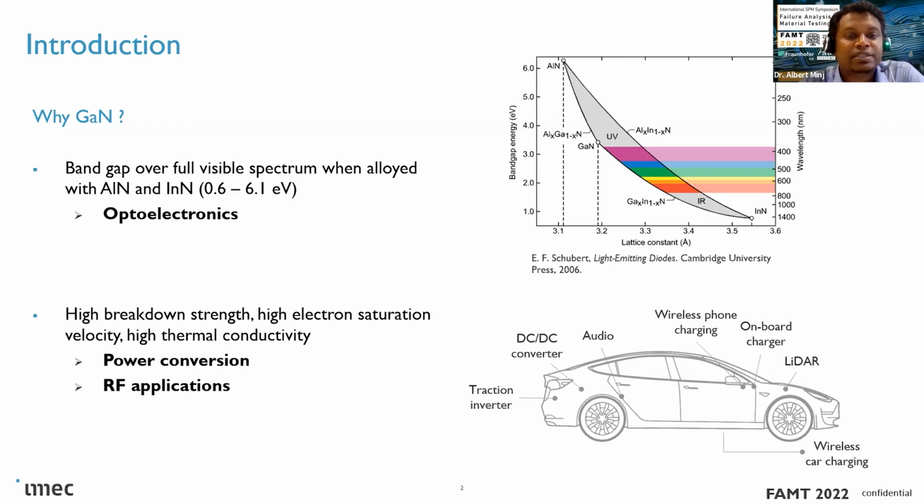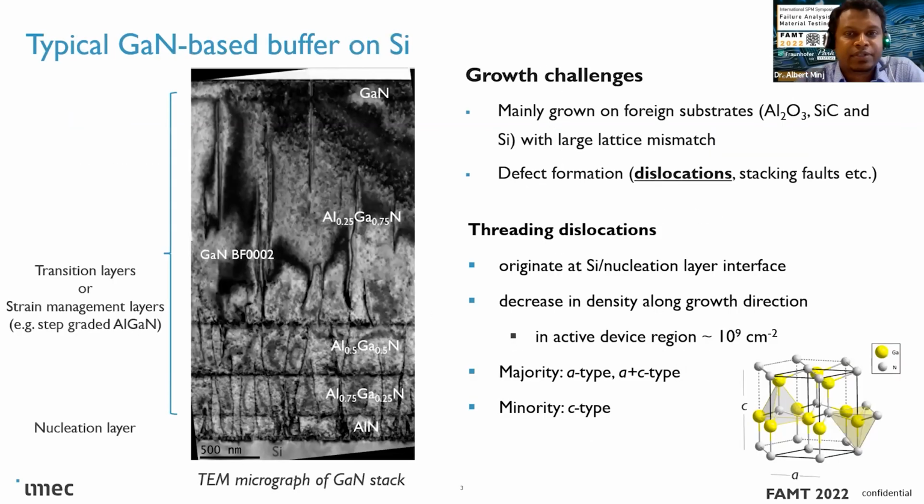It also goes beyond civilian applications into the military domain, where GaN devices are used for jamming unwanted signals. These materials still suffer from a large amount of intrinsically present defects, and it is almost hard to get rid of them at industrial scale without increasing the cost of production. This is mainly because there are no substrates available for growing gallium nitride, and currently it is grown on foreign substrates such as sapphire, silicon carbide, and silicon.